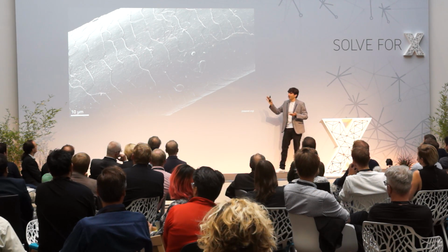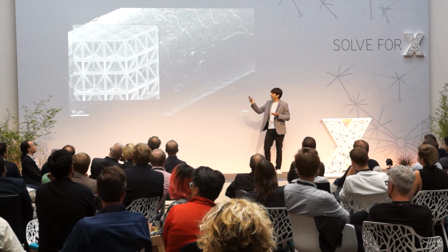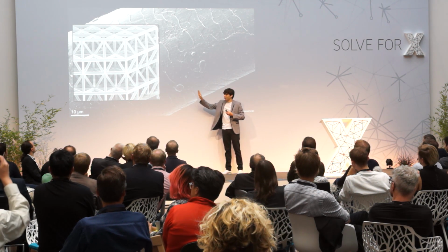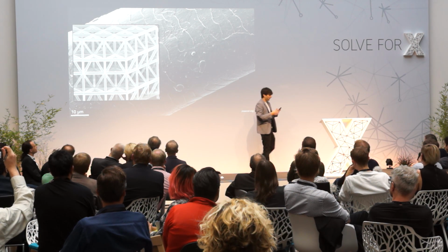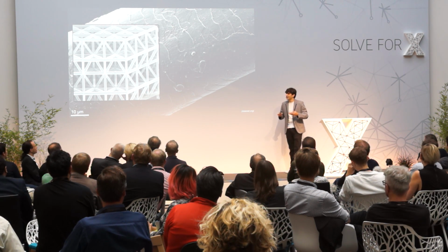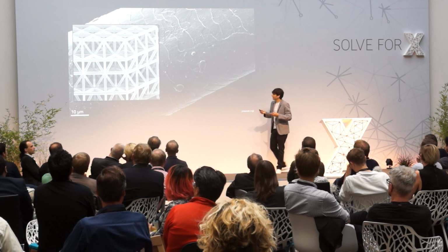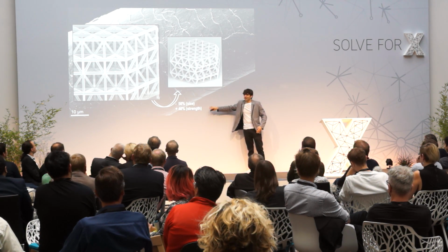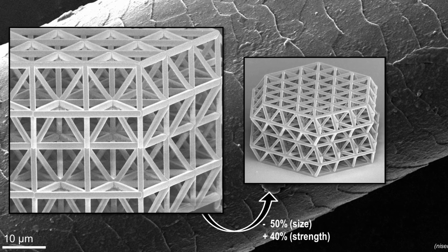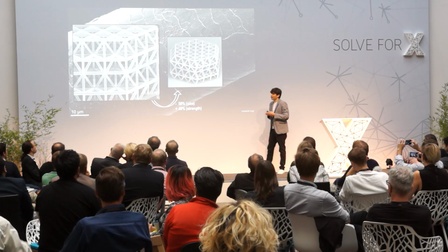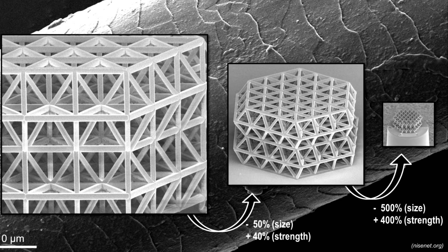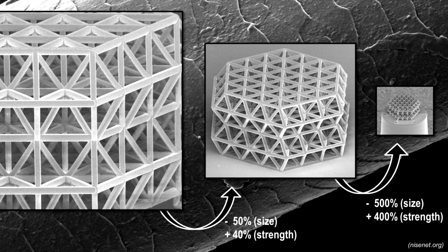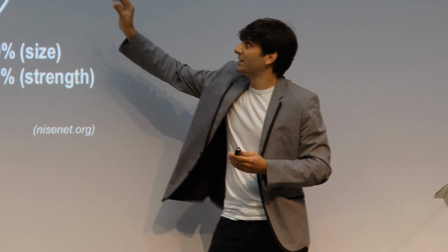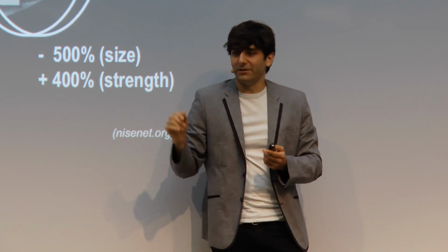This is a micrograph of a human hair. And now here we can see how small our structures are compared to that. Now, if we further increase the resolution or decrease the size of structuring, we managed to actually increase the strength again, so making it even smaller makes it even better. But this is still not the end. We found a way to increase the resolution by another 500%. And by this, a tremendous strength gain emerged of up to 400%. Now the unit cells of that very small lattice over here, they're not even 1 micrometer in size. And this is more than 60 times smaller than the diameter of that hair in the back.